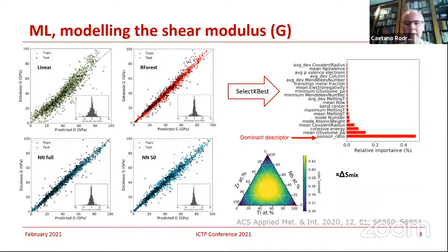So the d valence was part of it, but as you can see here, it does not come out as significant compared with the other features. One thing that we are very much interested in here is to have a model based on composition only for the elastic property. So even if it can be an important feature from the electronic point of view, for instance, in this particular case, where you're looking for the elastic properties, it does not come out as the one that is relevant compared with the other ones.